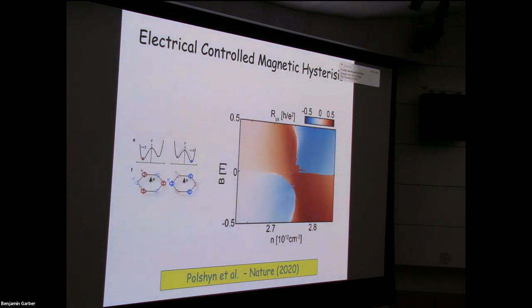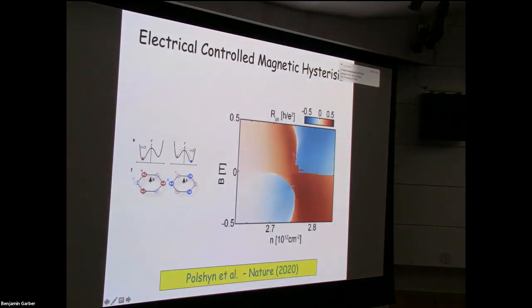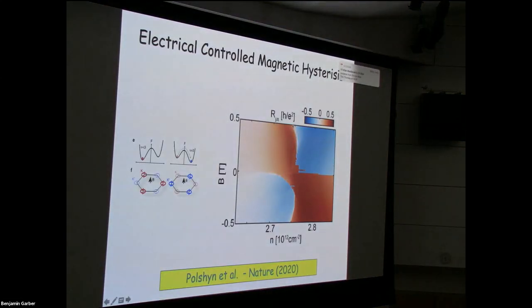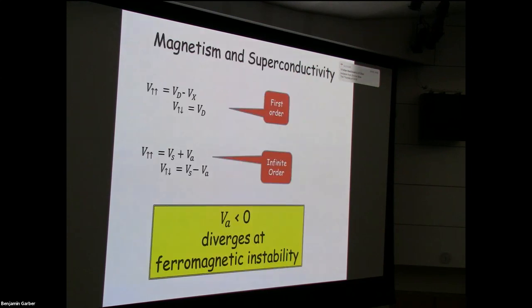I won't describe this in detail, but just trust me that the red and blue regions are showing that when you, in this experiment, move the Fermi level across the density at which the charge gap occurs, which is about 2.75 in this experiment, the magnetization changes sign. That certainly doesn't happen with spin-based magnetism. So that's kind of a curious property of orbital magnetism.